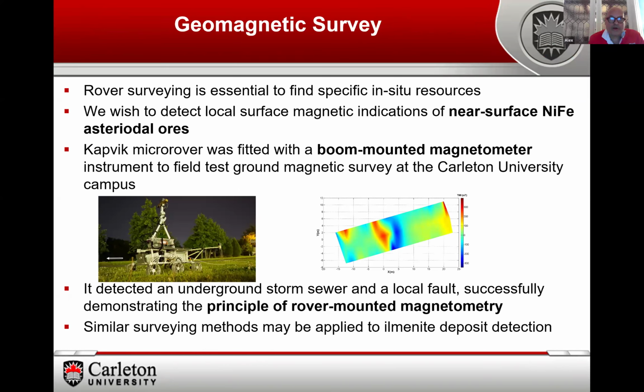When we were at Carleton, we decided to try to emulate whether we could find nickel iron material using magnetic surveying. We fitted our rover with a boom-mounted magnetometer and ran a magnetic survey of campus. What we did detect was an underground storm sewer and a local fault. So we demonstrated we can use magnetometry to potentially search for magnetic signatures.